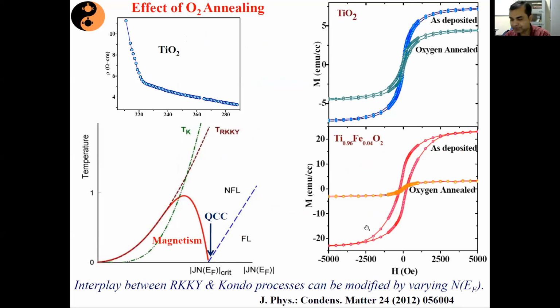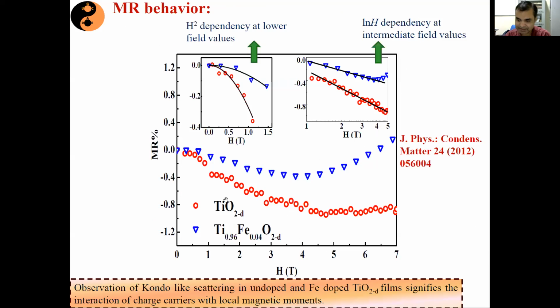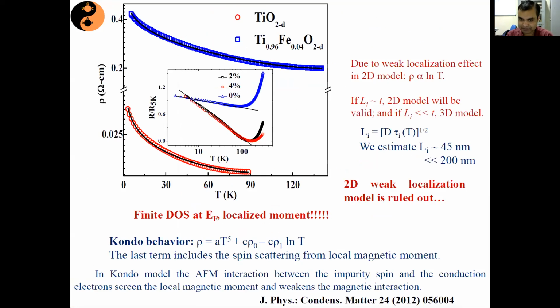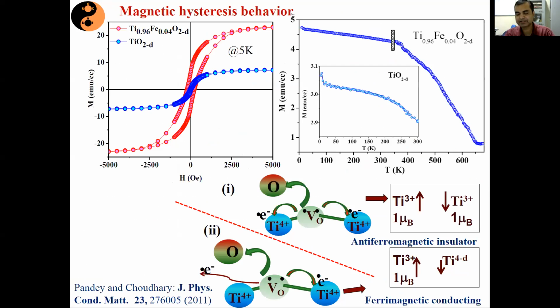Now, what is the origin of magnetization in the system? I said that iron was present in the ionic state, number one. Number two, is it really carrier mediated? That I confirmed from this magnetoresistance. Then the question arises, what was the origin of carrier in this system? Remember, in this TiO2, if you look at this particular cartoon, then I said earlier also that TiO2 does not like to be in the stoichiometric phase. It has certain tendency to form oxygen vacancy. And if there is oxygen vacancy in the system, that means it creates two free electrons available. And those two free electrons can act like a mobile charge carrier in the system. Okay, so those were the sources of charge carriers.